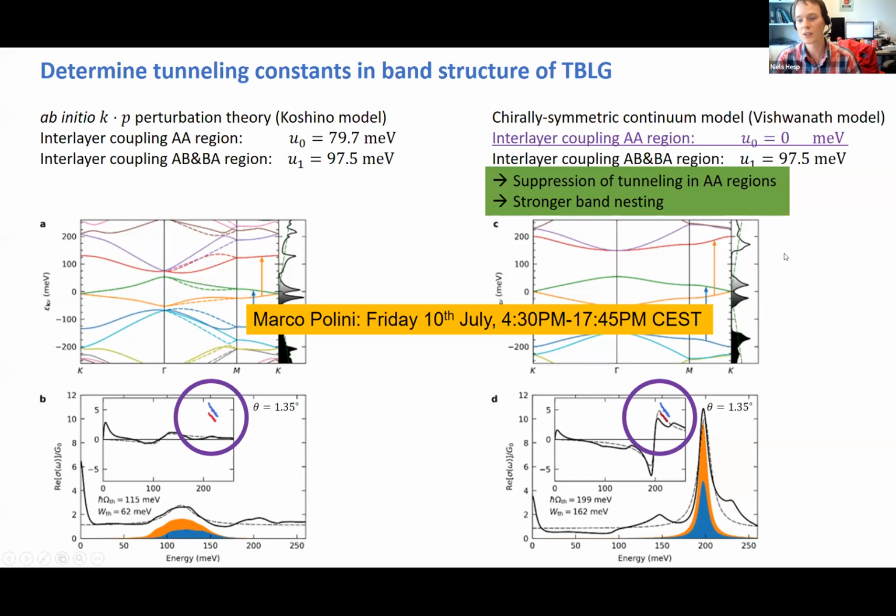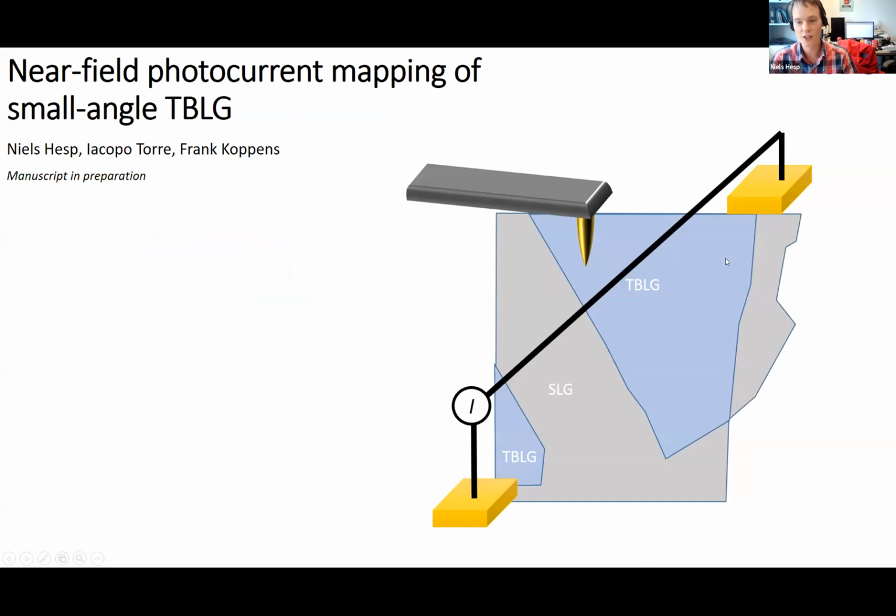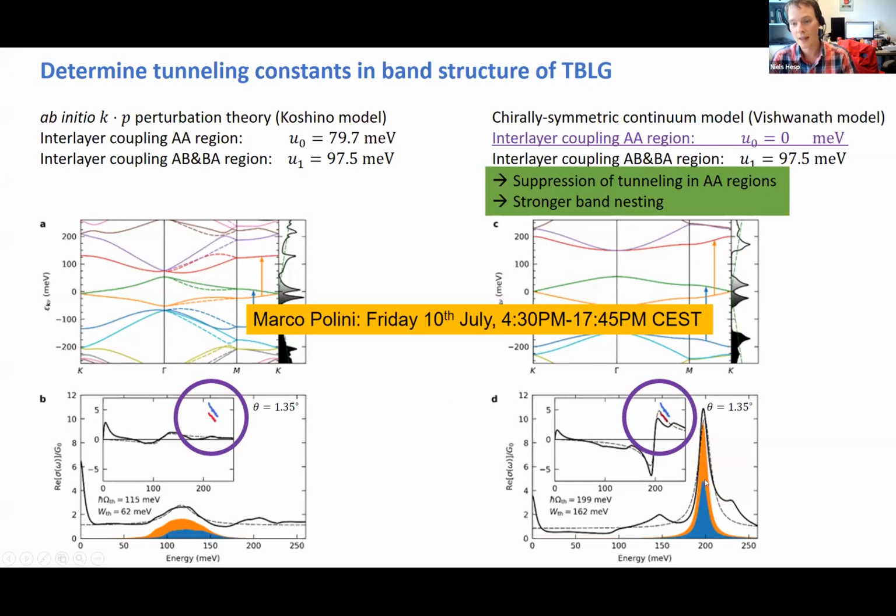Okay. Actually, this is not a fit in this case, there's an overlap of data, but the other parameter we can compare is the energy difference between these bands here. In that case, the match is best for an intermediate U0 value, around 40 millielectron volts, given the position of this absorption peak. I see. Okay, so it's 40. Okay, good. Thanks.